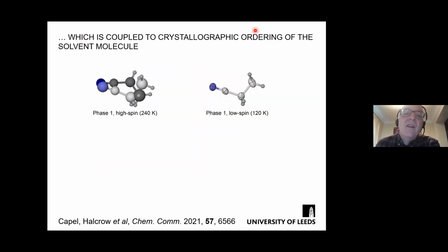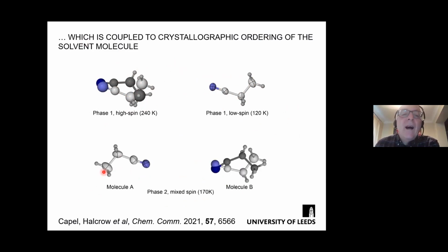And we can understand this, I think, when we look at the solvent in the crystal. In the high spin crystal, the solvent is disordered, 50% up, 50% down in its orientation. In the low spin phase, the solvent is now completely ordered in one position. And in the intermediate phase, we have two unique solvent molecules. Now, one of them is ordered, but the other is still disordered. So the existence of the intermediate phase, I think, is actually controlled by the ordering of the propionitrile solvent, not by the spin states of the molecule of the complex.